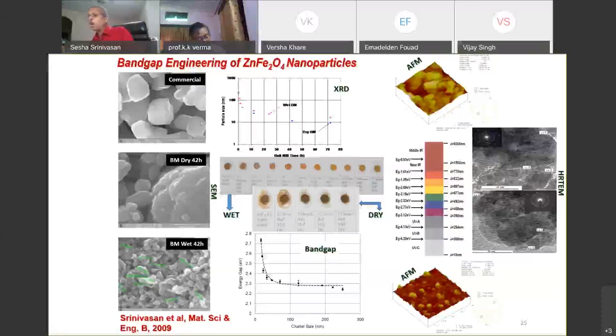Then we try to correlate the band gap with the crystallite size. The crystallite size goes down from 200 to 10 nanometer. The band gap goes down as well, from 2.7 electron volt to 2.3 electron volt. We did this process with wet ball milling or dry ball milling, trying to adjust the band gap so that it works suitably for either hydrogen production or wastewater photocatalytic oxidation treatment.